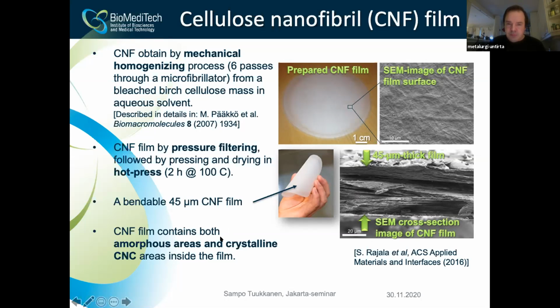In this case we have used the CNF gel as a starting material. It contains both crystalline and amorphous areas in the film. And here we have some images. You can see the surface SEM image of the CNF film, and below you can see the cross-section. You can see some layering of the film, because there's some self-alignment of the cellulose, because it has a lot of van der Waals forces and hydrogen bonding between the fibers, so it forms this kind of layers because of that.